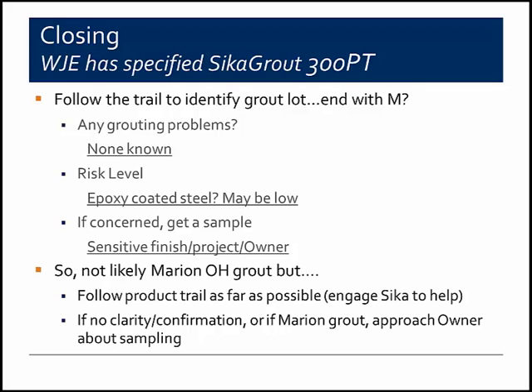Also, what is the risk level? If there is corrosion, what is the risk? On this project, I believe epoxy-coated steel was used for the retrofitting as opposed to uncoated strand or uncoated steel. So even if the chloride content is high, for this particular project, the risk of corrosion would appear to be relatively low. However, at the end of the day, if you're concerned, the best way to know what you've got is to get a sample. It's a little challenging on this project because it's a sensitive finish, sensitive project, and an owner we'd rather not ruffle feathers with, but it may be warranted given the circumstances.